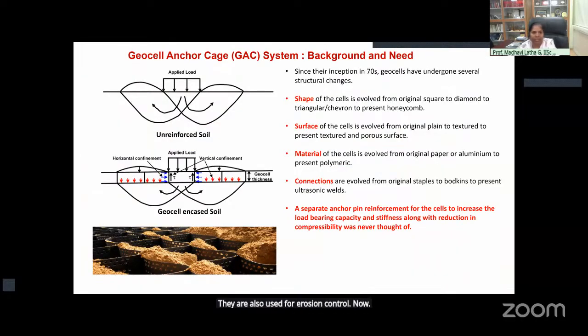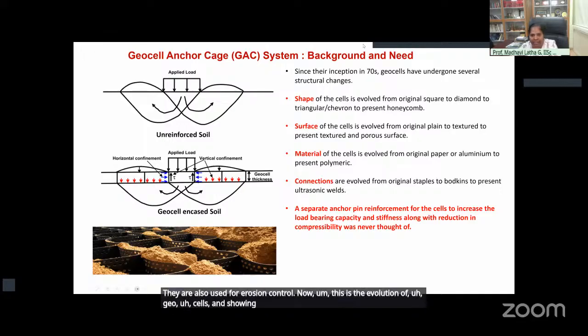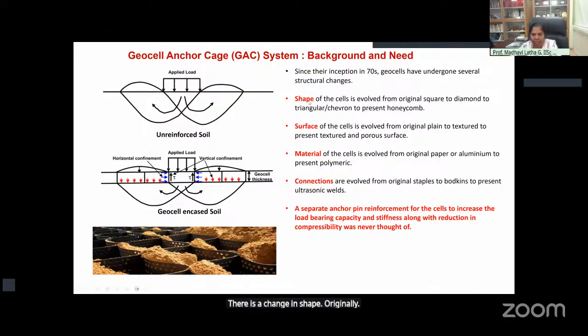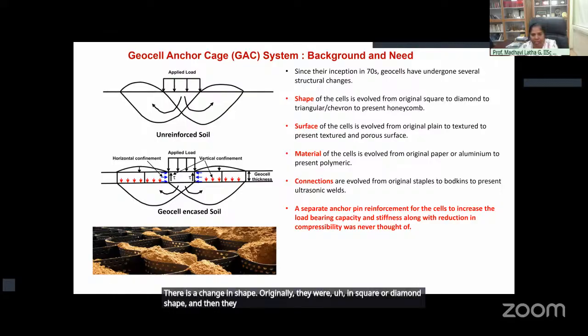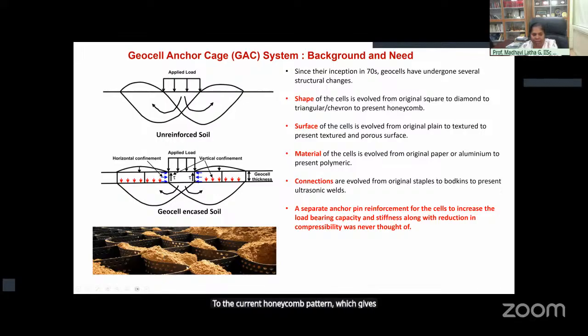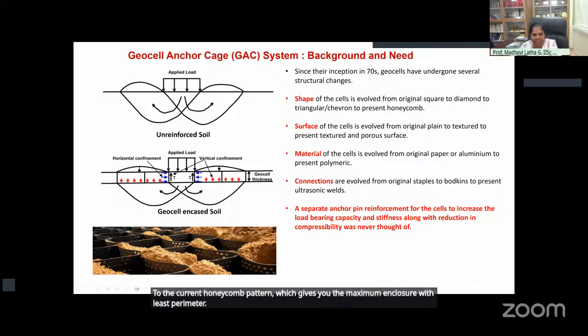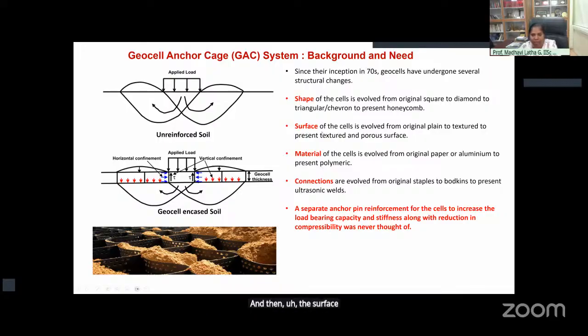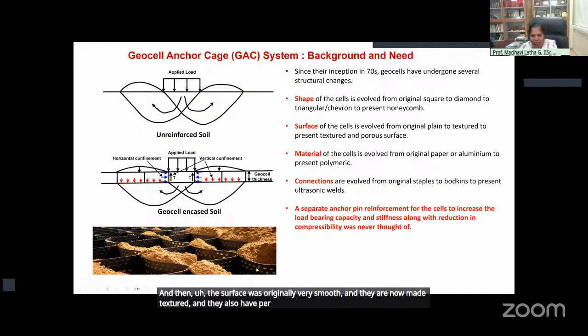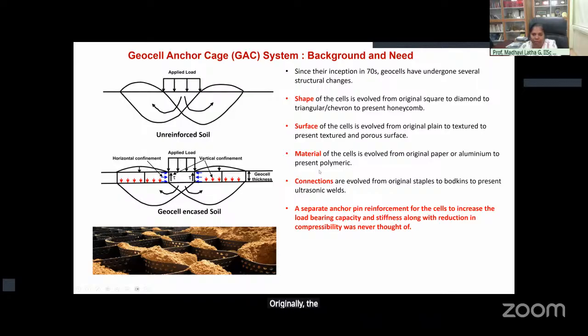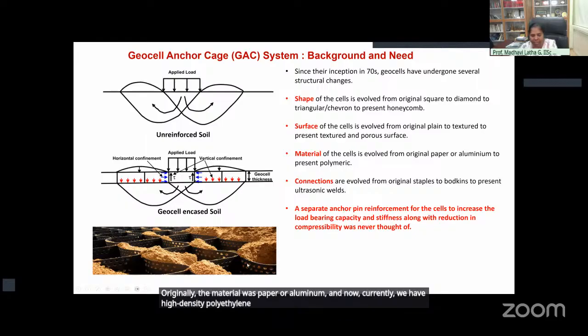Now, this is the evolution of geocells I am showing here. And since the 1970s, there is a change in shape. Originally, they were in square or diamond shape, and then they moved to triangular chevron patterns to the current honeycomb pattern, which gives you the maximum enclosure with least perimeter. And then the surface was originally very smooth, and they are now made textured, and they also have perforations to allow drainage. Originally the material was paper or aluminum, and now currently we have high density polyethylene and polypropylene geocells.